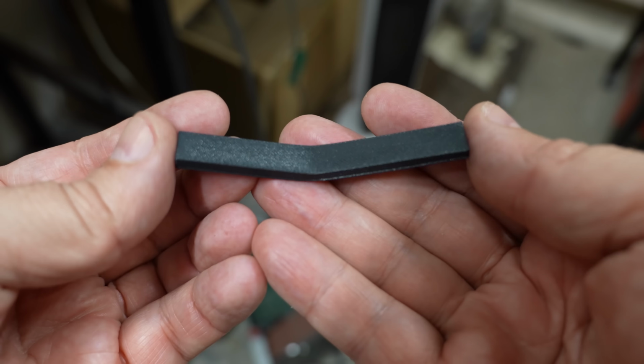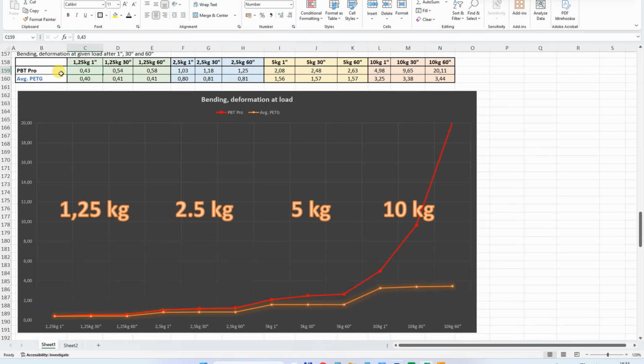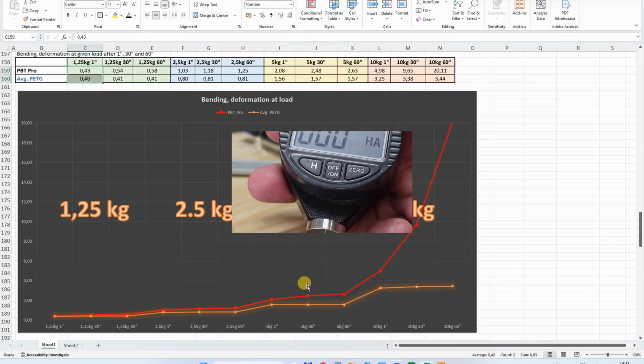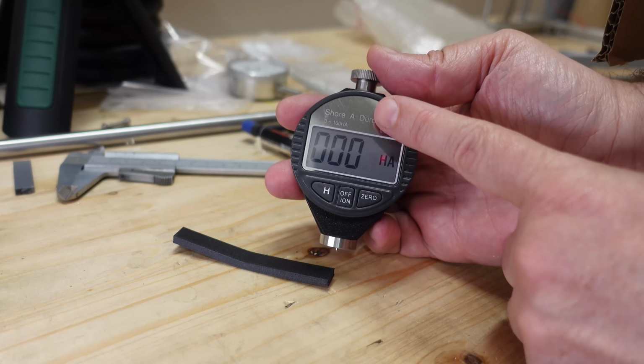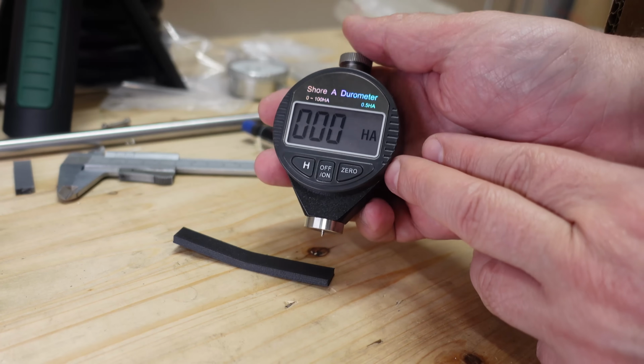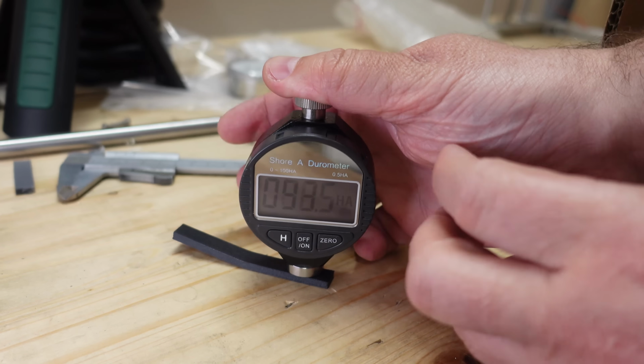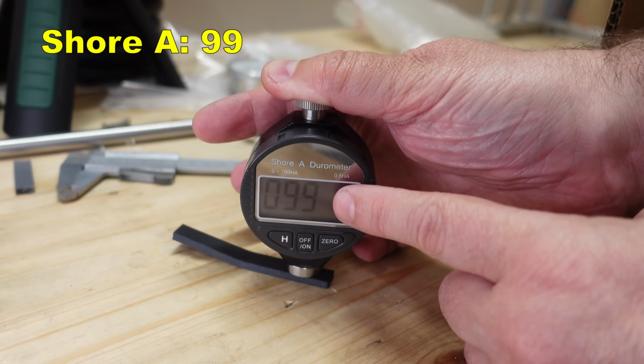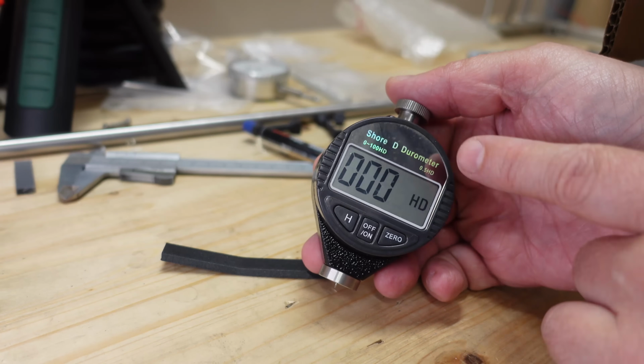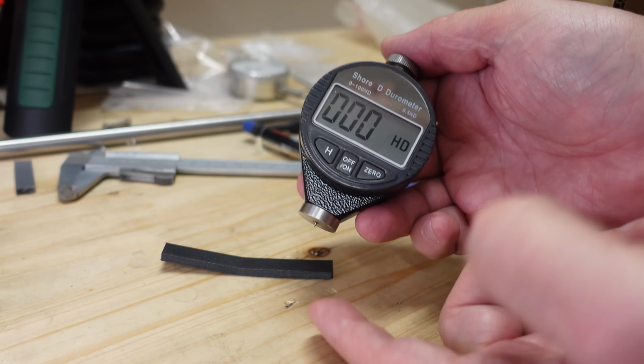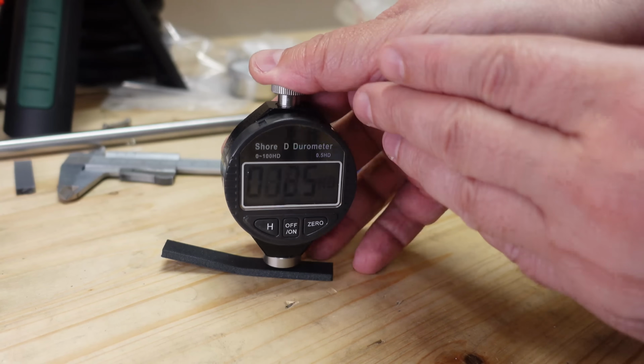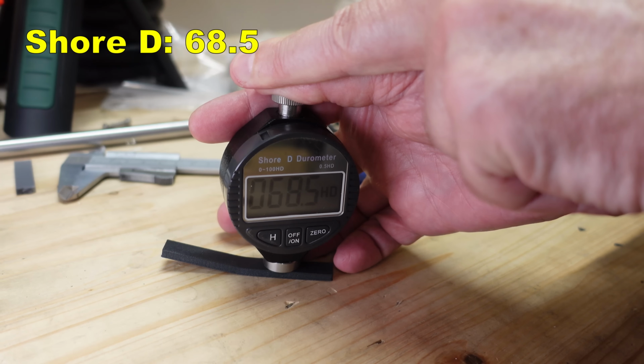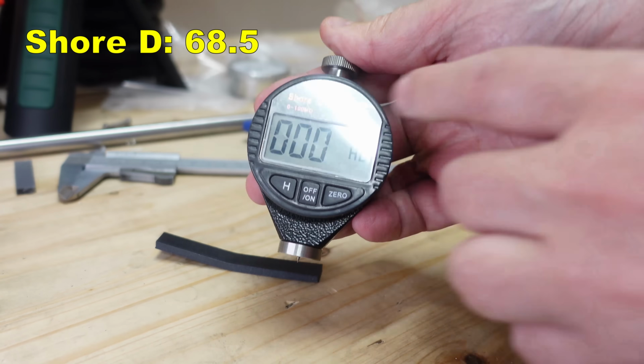Wow, look at this permanent deformation. It had very similar initial deformation to PETG, but after this it constantly deforms under any tested load. Definitely you don't want to use this PBT Pro for parts which will be under constant bending stress. I became curious about the hardness. This is a Shore A durometer and I will measure on the top covering layer. 99 on the Shore A scale. And what about Shore D hardness? This is sharper and the penetration will be bigger. 68.5 on the Shore D scale.